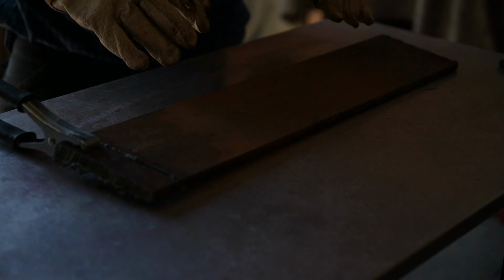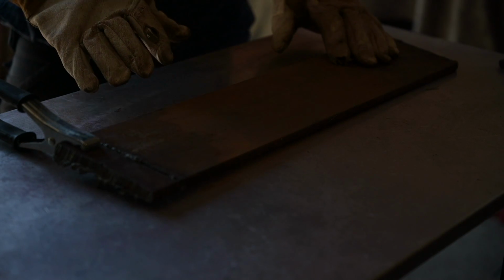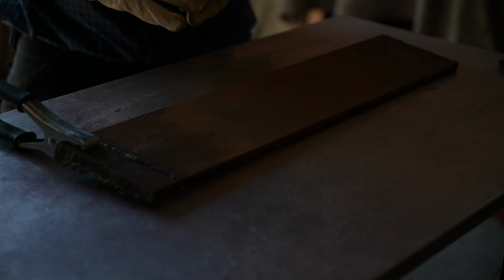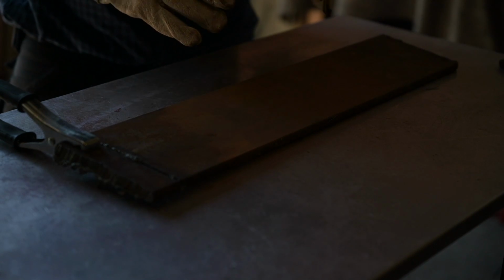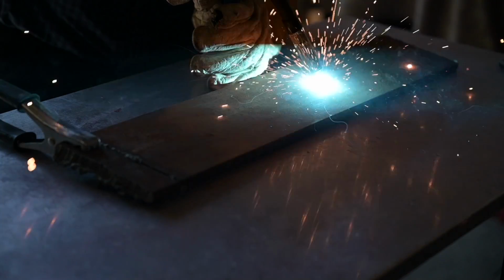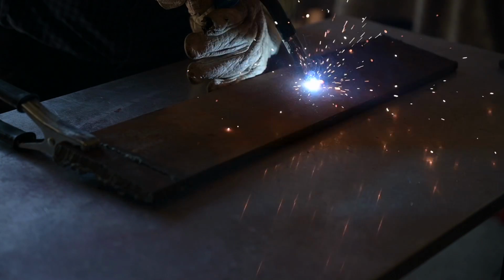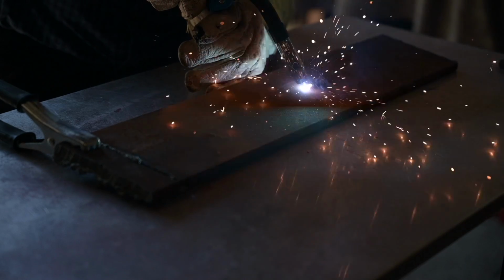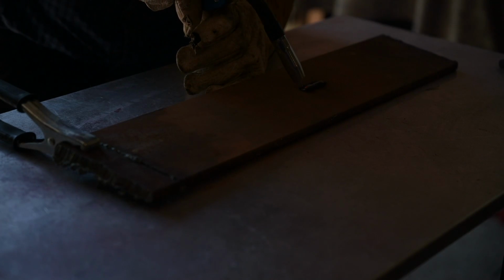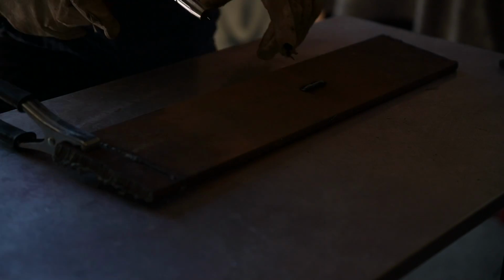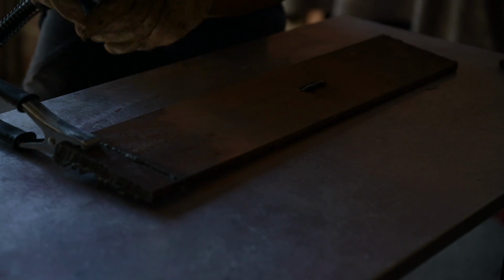Alright, I got a thick piece of metal here and I have set the welder to MIG mode, and my wire speed is about 4.8 meters per minute and my voltage is about 15 volts. So I'm going to try to pull a little line and then see how that goes. And that goes very smooth, but as you can see, it is also very much on the surface.